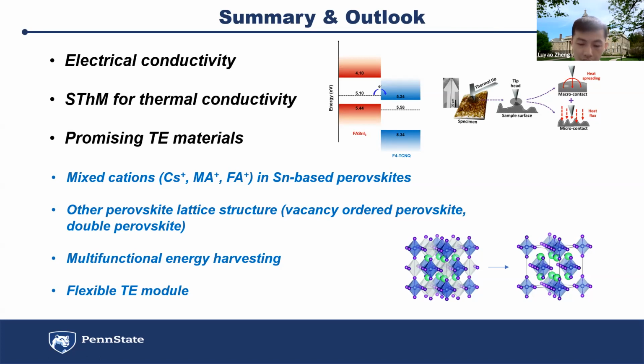And because perovskite, we know, has 3 sites, ABX, we can try to change the different elements on these 3 sites to obtain new materials and see what we can get for the thermoelectric performance. And also we can try to mix the cations. We have these 3 mixed cations inside of the perovskite, so the phonon scattering will become even stronger. It can scatter different wavelengths of phonons and will induce even lower lattice thermal conductivity.